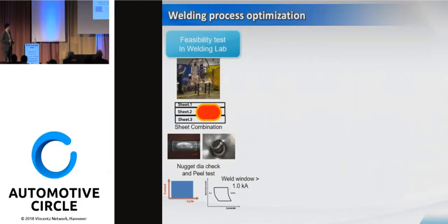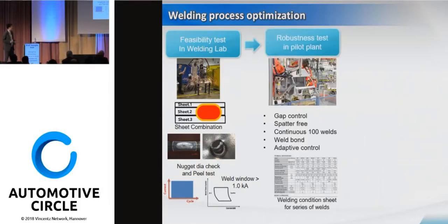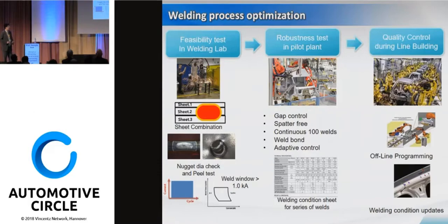They check the nugget diameter or button diameter, also do the peel test, and come up with this welding window for each combination. And then they moved on to the robustness test in the pilot plant. They check the gap control, spatter-free, continuous 100 welds, weld bond, and they come up with this welding condition sheet for this pilot plant. And then they threw this one into the quality control during the line building here.